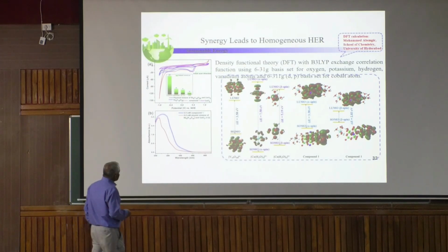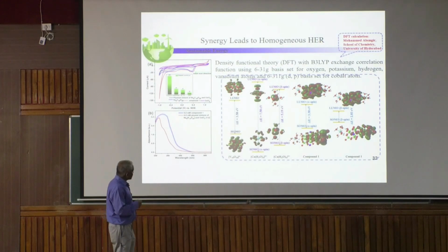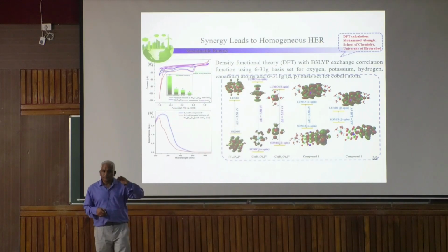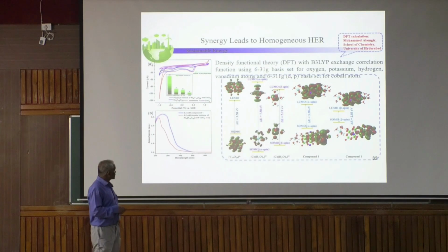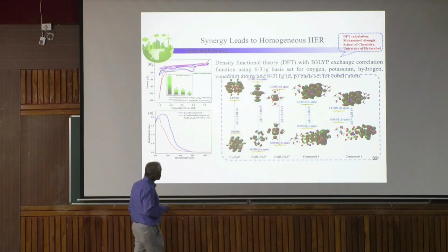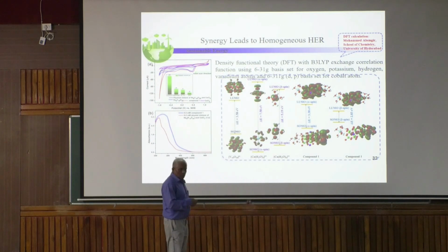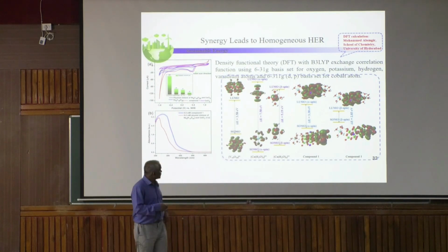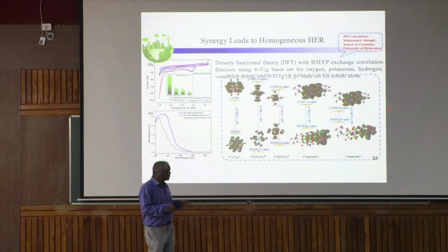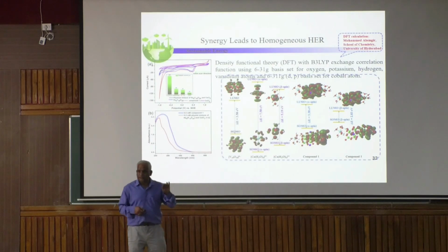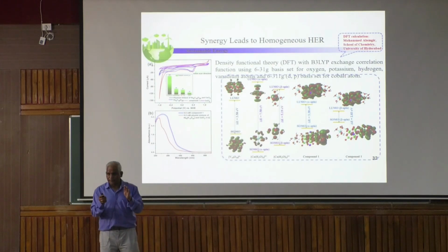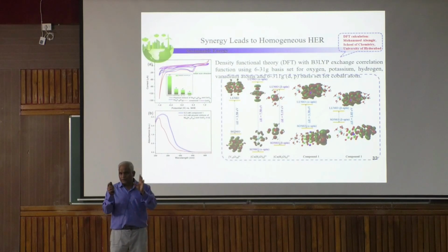So this is the HOMO-LUMO gap of the cluster. Now cobalt 2 will have two spin states, alpha state and beta state. The beta state gap is smaller than the alpha state. And if you see now our compound, the compound we got as single crystal, for the alpha state this is the gap, and for the beta spin this is the gap. That means beta spin is the better one. A synergy is established when you get this. They talk to each other, because the vanadium cluster and the cobalt system talk to each other. A synergy is established, then only it happens.